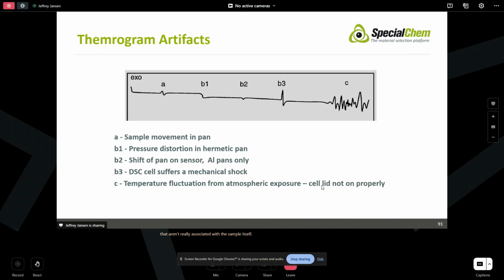So there's a lot of them, and you want to be able to recognize them. Once in a while, we see an electrical blip, an electrical spike, and that can look something like this. This can also be mechanical. If the sample actually moves, you can see that sometimes. The sample moves on the pan because it pops if it's got a lot of water in it, and the water comes off, kind of like a kernel of popcorn. Sometimes it can move. Again, sample movement in the pan, that this and this can look alike.